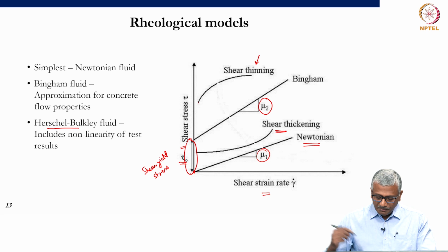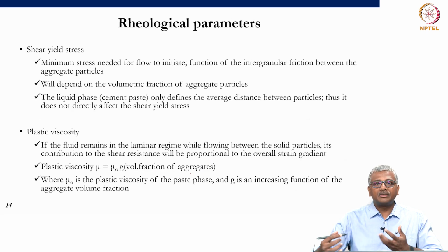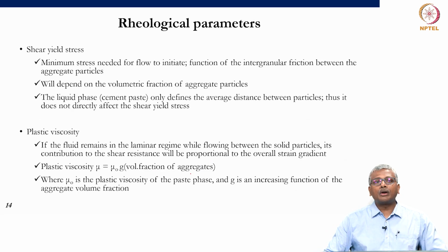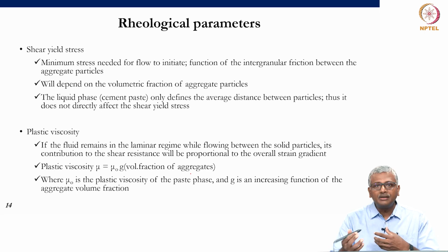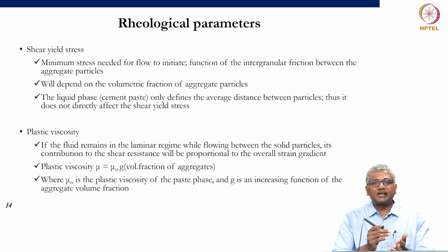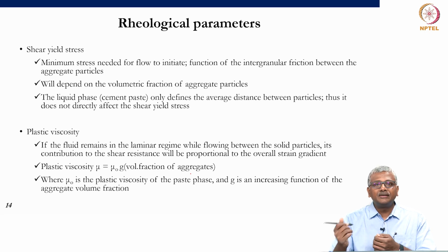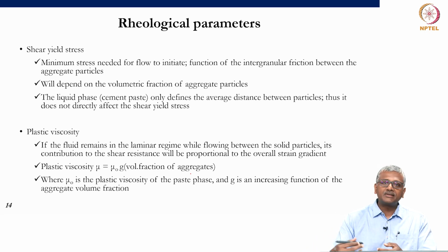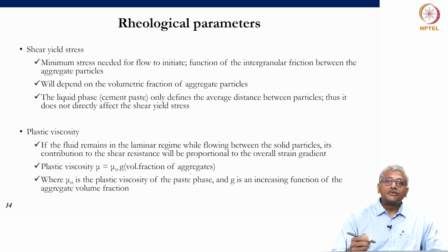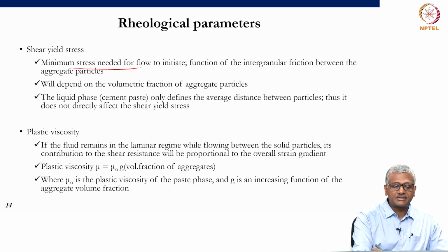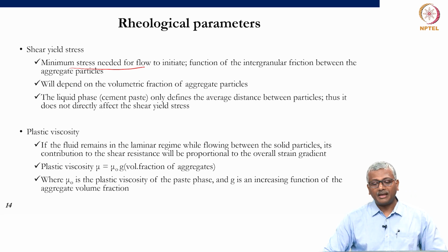Now, in simple terms, let us take a look at what this means physically for concrete. Concrete is a composite material where aggregates, that is coarse and fine aggregates, are suspended in the cement paste. As we said earlier, cement paste flows, the aggregates basically will be carried by the cement paste, right. So, the more the aggregate, the more difficult it will be for the cement paste to carry the materials. That is why when you have more paste, the workability is more, right. So, shear yield stress relates to the minimum stress needed for flow to initiate, and it is a function of the intergranular friction between the aggregate particles.